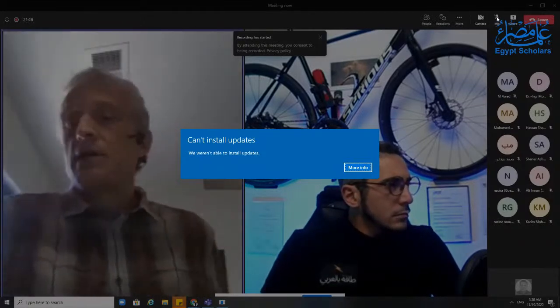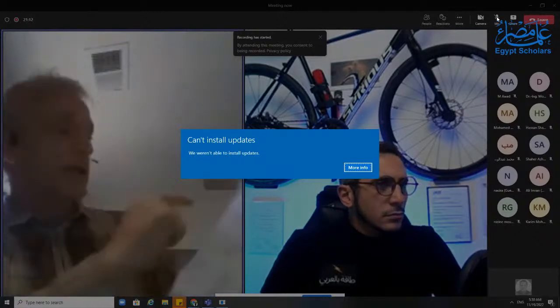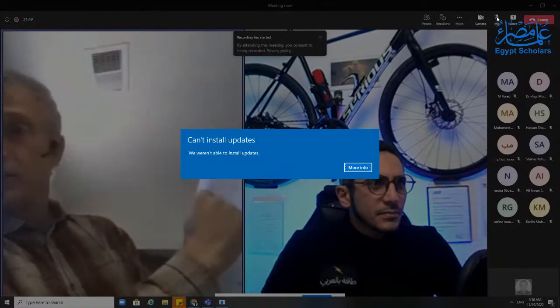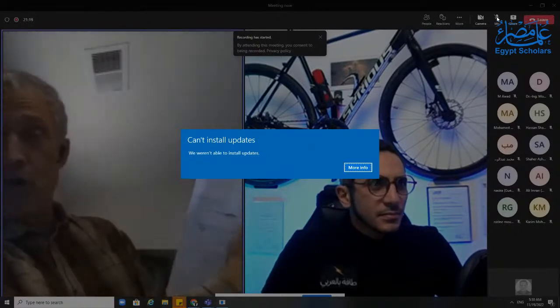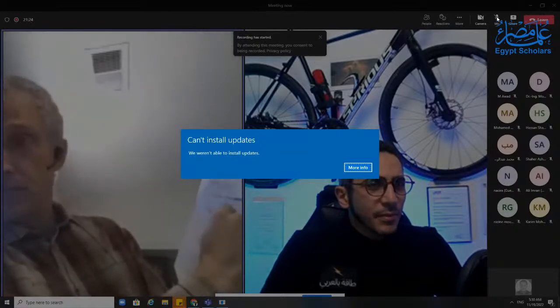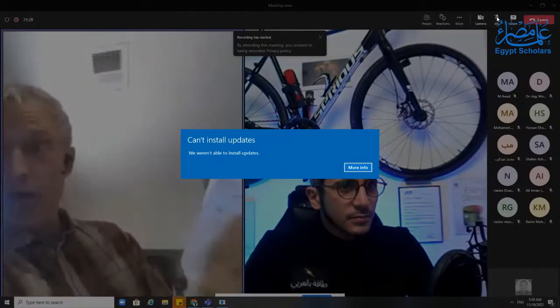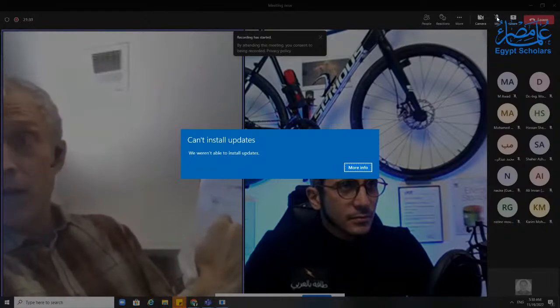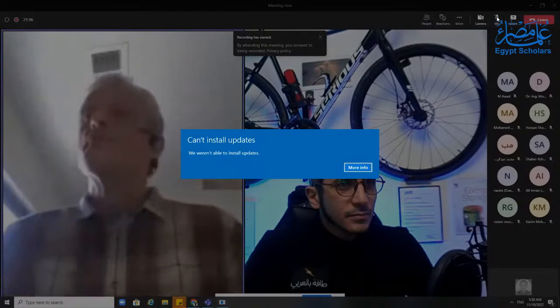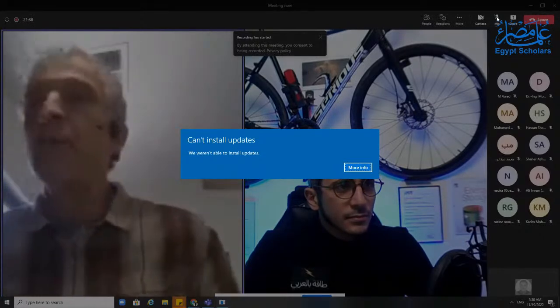And you say, well, it doesn't matter because you're a production engineer. The recipe I have says that first I add this amount of this, and then I add this amount of this, and I dry mix it for this long, and then I add some liquid and I mix it for this long, and then I add some of this powder, and then I add some pixie dust, and I mix it for this long, and then I measure my properties with a complex rheometer, and I get these properties to prove that my quality is good, and then I can send it to the next step. I am telling you that's not good enough.